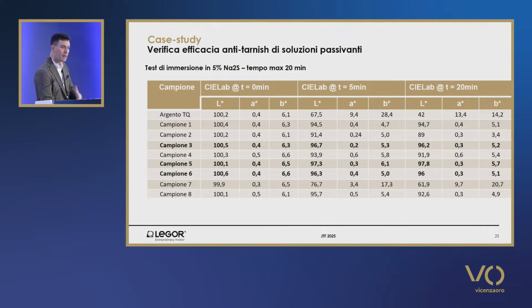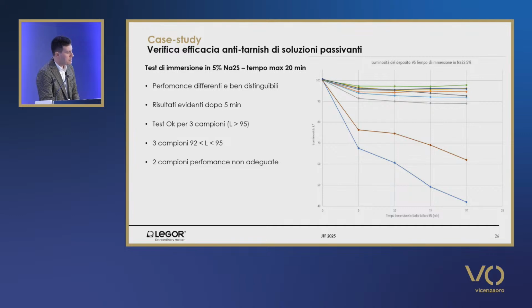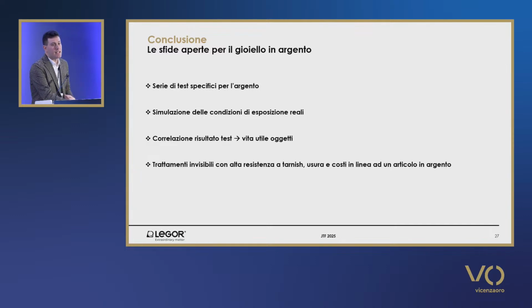And then this test was made, and in this case, after the first 5 minutes, we could see differences between the various products. And at the end of the test, lasting 20 minutes, results were confirmed. There were no significant changes. If you look at the L value, which is the brightness and the white color of the silver alloy, you can see that there is a difference between the various treatments, and after the first 5 minutes, results are evident. 3 samples overcame the test with a brightness greater than 95, and all the other samples did not achieve the same results.